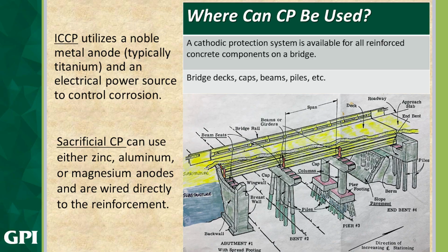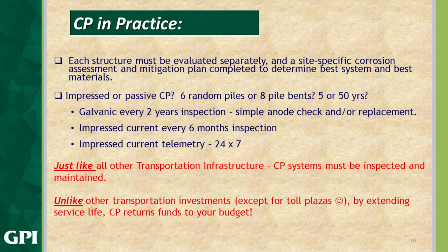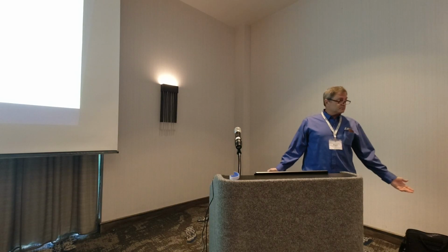Sacrificial CP uses zinc, aluminum, or magnesium anodes, and these anodes lose volume as they sacrifice to protect the steel. So in practice, each structure has to be evaluated, and you have to do a corrosion assessment for that specific structure. Can't emphasize that enough. That's the only way to determine the best system and the best materials, period.